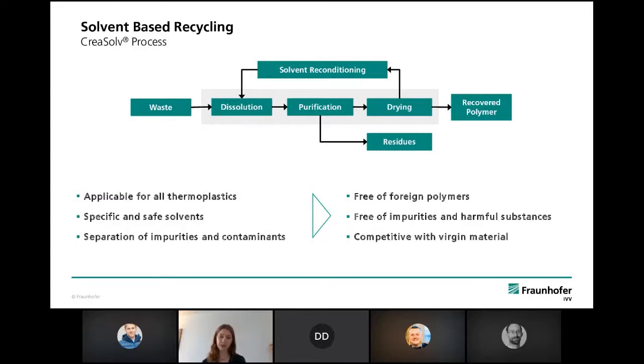In other cases, the filtration residues might be the materials that we aim for in our recycling. This is the case, for example, if we have one bulk material and only a small amount of a thermoplastic polymer that prevents this material from being recyclable. This is the case with many of the DECOAT input materials, because we have a bulk material and then there's the coating, and this coating can be removed from the substrate if it is thermoplastic by dissolution. Another use case also in the DECOAT process is when we have cross-linked coatings, and those also can be removed, for example, by dissolving a primer that is underneath or by swelling the coating. And those three examples of the CreaSolv process I will present now in examples.